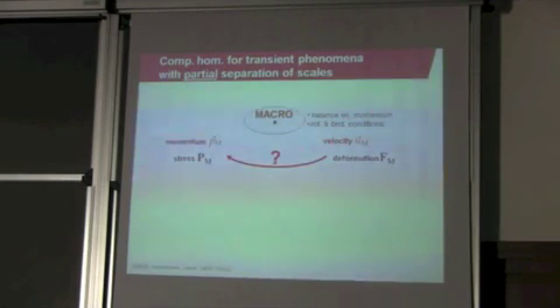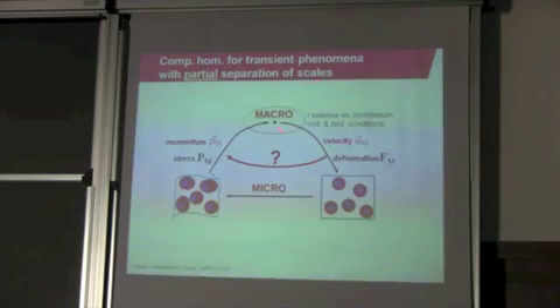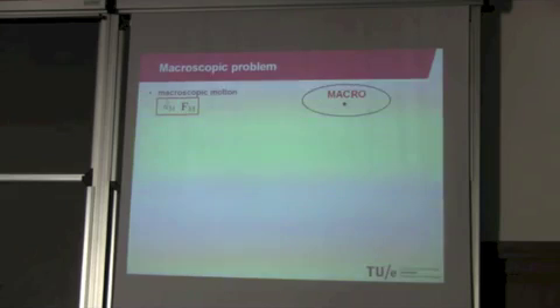So what do we then need to do? Again, at the macro scale we want to solve the balance of linear momentum. But now at each point and each time instance, for a given velocity and deformation, we want to know as a response the stress, but also the momentum, since the momentum is now not a simple trivial expression, so it has to be somehow computed from the microstructure. So we need to build up a microscopic problem, and we need to consider several steps. How do we go from the macroscopic scale with these kinematic quantities onto the microscale? How do we link the scales kinematically? How do we formulate our microscopic boundary problem in such a way that it's linked to the macroscopic problem? And how do we at the end extract the dynamic or kinetic response of the microstructure in terms of the momentum and the stress?